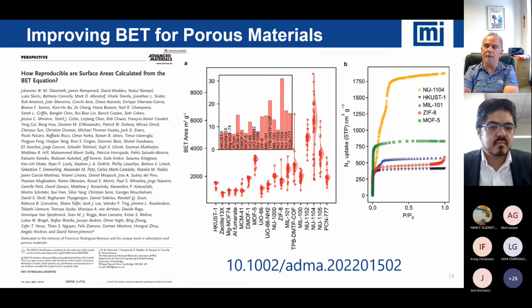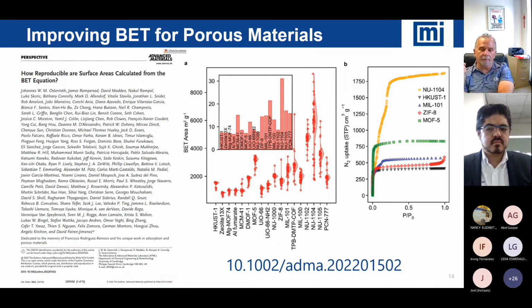This was clearly sharing it, and what we discovered from the process was that even though the rules that we all used apparently were the same, there were many different ways that people calculated it and their considerations for the calculation. So a few things that came out of this is that the raw data, the actual adsorption data, should always be reported. And whenever it's possible, if you can include that in your supplementary information, that